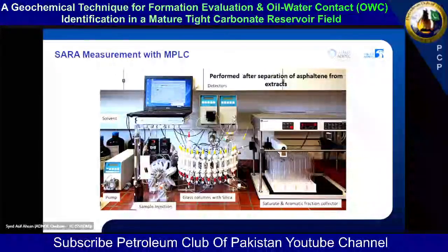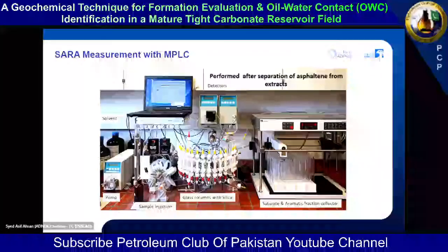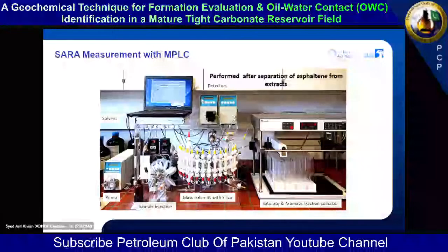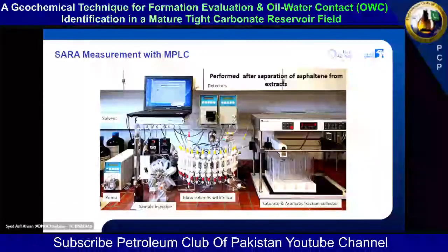And then finally, you extract the silica-filled column with the third solvent for resins and asphaltene. Okay, so this is how you separate using the organic solvent. This is a tedious, lengthy process. And then, of course, you have to evaporate the solvents to measure the quantity of saturates and aromatics.